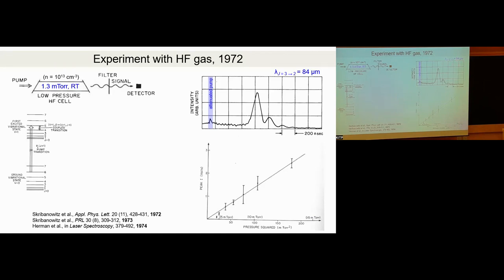They saw, in the time-resolved experiment, that after excitation and some time delay, the gas produces a very bright pulse of light, which decays in an oscillatory manner. They measured the peak intensity versus squared pressure. So you can think of it as n squared on the x-axis. And they saw that indeed the intensity of this peak scaled as n squared, as one would expect. So they said that this is Dicke superradiance.